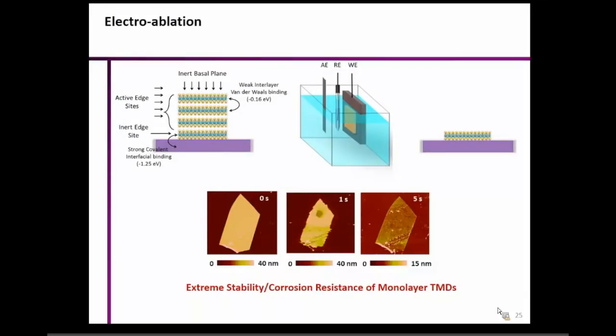So what happens is that in the last layer, your edges are interacting strongly with the substrate, and now the edges also become inert. So your basal plane is already inert, your edges are now also inert, so you cannot really etch this monolayer. And that makes them so much superior when it comes to electro-oxidation and corrosion processes.